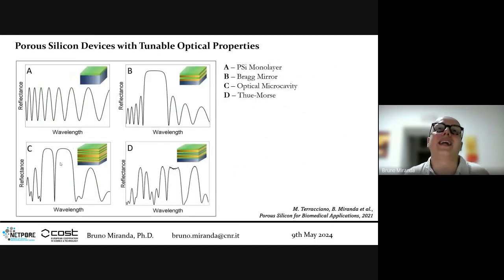It's important to know the refractive index of porous silicon because you can tune the optical properties according to the different geometries you want to create. For example, with a simple monolayer of defined porosity, you can predict its reflectance. With a monolayer, you have interference—constructive and destructive—so you have increase and decrease of reflectance as a function of wavelength.